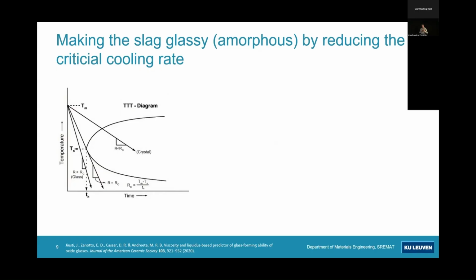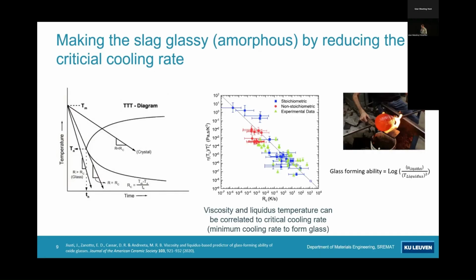So we have to actually reduce the critical cooling rate. The critical cooling rate is the rate at which you cannot form any crystals anymore. If you put it in a TTT diagram, then that's the line on the left, which you have to obtain. Experimentally, this is difficult, but it can be done. But there's a nice gem I discovered some time ago, a nice paper which was linking the critical cooling rate to the viscosity and liquidus temperature.